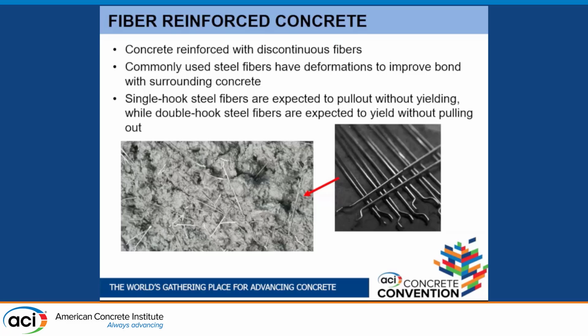As you can see in the photo on the right, steel fibers typically have deformations to provide for mechanical anchorage with the concrete. Now, normal fibers, let's say this one with a single hook, are designed to slip rather than to yield as a crack opens. So as a crack opens, any fiber bridging that crack will tend to slip. There will be some local yielding at the ends where the hooks are, but along the length, they are not really expected to yield.